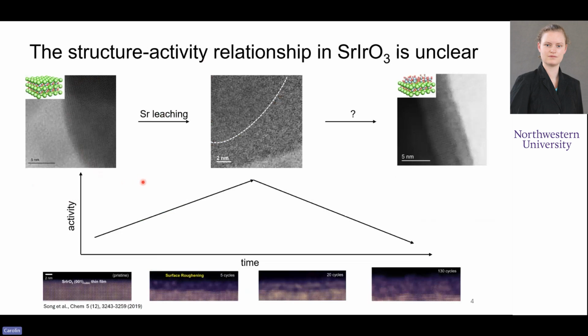It has a clean crystal surface. And then as it is used in the electrolyzer in the acidic environments and oxidative conditions, the strontium starts to leach out and results in this reduced crystallinity surface here. And you can see over time that this amorphous surface forms on the catalyst. And it maintains that kind of morphology. What's interesting, though, is that initially, as this catalyst is used and this surface becomes amorphous, the activity actually increases and it performs better. And then over time, the activity drops until it eventually dies.